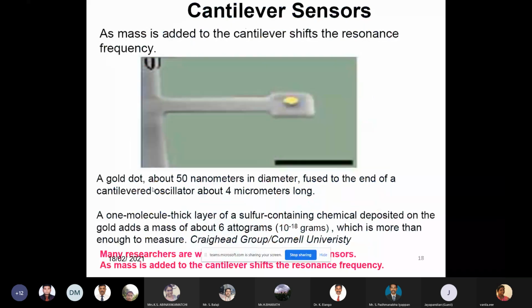For example, the Cornell University people used a 50 nanometer gold dot coated with sulfur by chemical deposition. Then they wanted to measure what mass of sulfur coating is loaded on the gold dot. For that, they used a 4 micrometer length cantilever. The gold dot is 50 nanometer. They proved that they measured the sulfur coating to be 6 attograms, 10 power minus 18 grams.